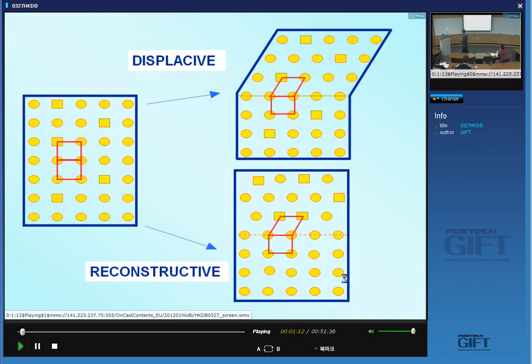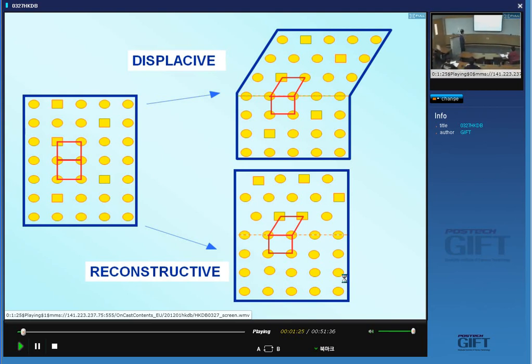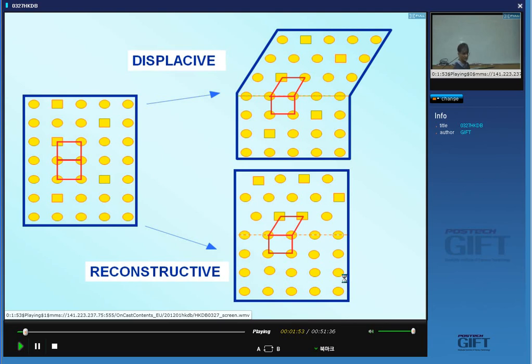There is an atomic correspondence between the parent and the product phases because the neighboring atoms are not actually altered in their relative positions. On the other hand, when we have a reconstructive transformation we achieve the change in the crystal structure by breaking all the bonds and rearranging the atoms so that there isn't a large amount of strain energy created. We can imagine this transformation to occur in two steps.